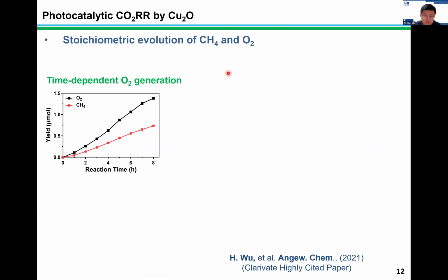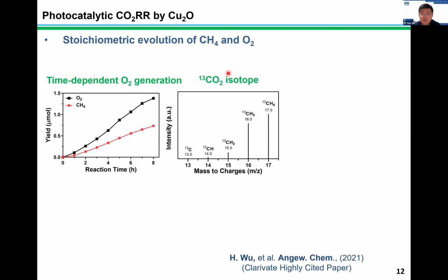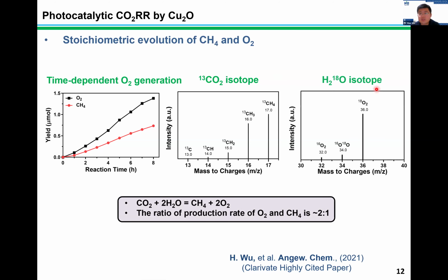In the meanwhile, since we involve the copper-based MOF in the photocatalyst design, which is a carbonaceous material, we were wondering if the produced methane is indeed from the carbon dioxide reduction reaction. To prove that, we use GC-MS and isotope experiments. We're using carbon dioxide with carbon-13 and oxygen with oxygen-18. The results collectively suggest that the produced methane is indeed from the carbon dioxide reduction instead of a parasitic reaction of the photocatalyst itself.